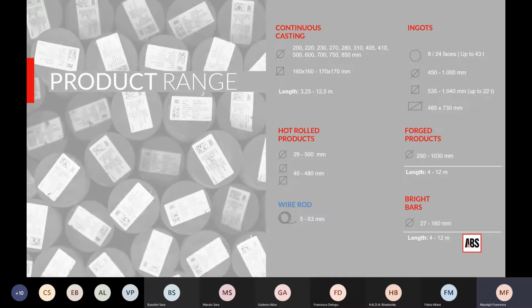I would say this is one of the strongest points of ABS because basically we start by rolling 5 millimeter wire rod, and we can deliver up to forged bars with a diameter of 1 meter. In between, we are really covering almost any possible product in either round or square shape.